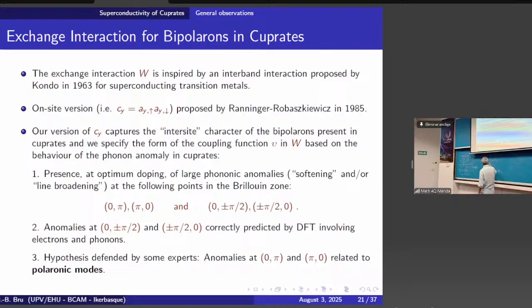I haven't said what this is. It means that on some quasi-momenta there is a gap. So maybe for quasi-momentum k equals 0 there is no gap, but for quasi-momenta k equal in particular to (0, pi) there is a gap. And it's shown experimentally that the gap is at (0, pi). It corresponds to this E_k, so a special case with a gap, and maybe for k equals 0, the Fourier transform of V is 0, and then there is no gap. And so what we need is a function V which is peaked around this mode. This is a natural candidate.